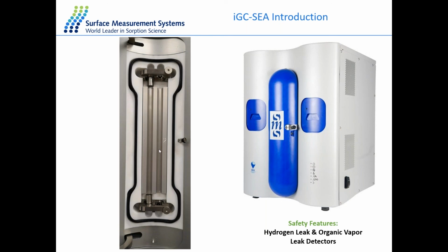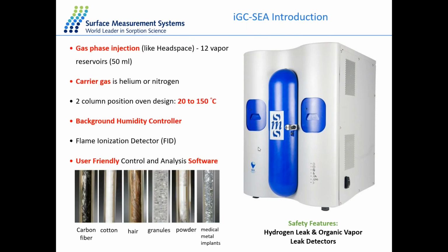Each column is surrounded by a column oven, and the column oven can go from 20 degrees to 150 degrees. We also offer a background humidity controller. So if you want to analyze your materials at different levels of humidity, you can also do this, and in this case, one of your reservoirs will have to be water. We have a flame ionization detector, and this is to accurately measure the concentration of the organic vapors. We also have some safety features, so hydrogen leak detectors and organic vapor leak detectors, and these can be found all on the panel here.